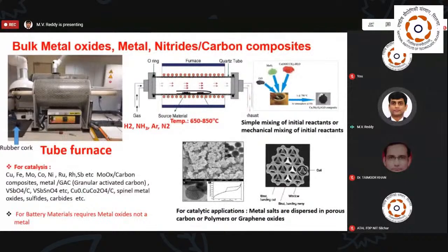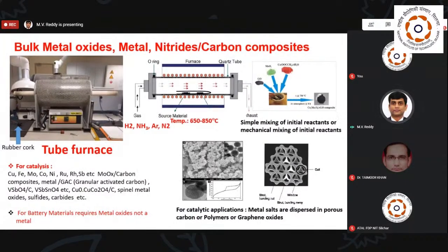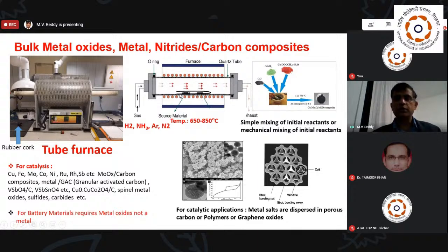For example, you want to prepare some nitrides, such as boron nitride, or for particular applications you need a nitrogen containing hard material, for example chromium or vanadium nitride. The best way is that you prepare the respective oxides, or thin films is the best way you can go. Otherwise, if you want large scale, you can use a simple tube furnace. You pass the respective oxide with ammonia gas, and we can get it. Again, remember this is a bulk one.